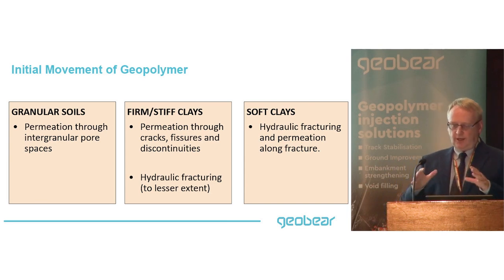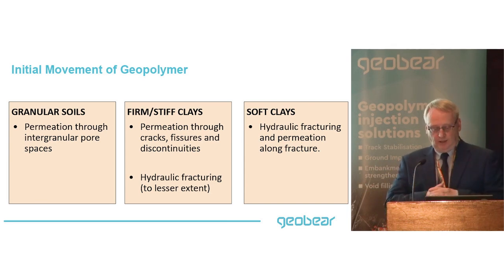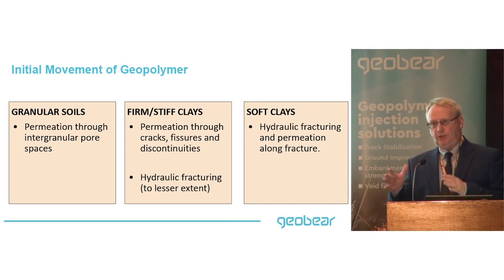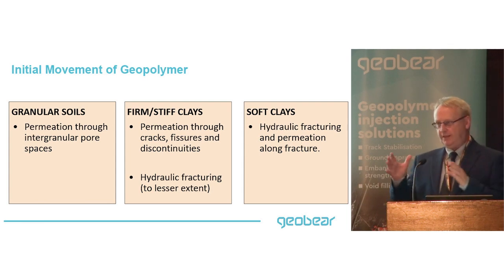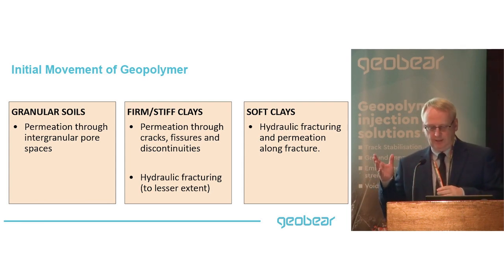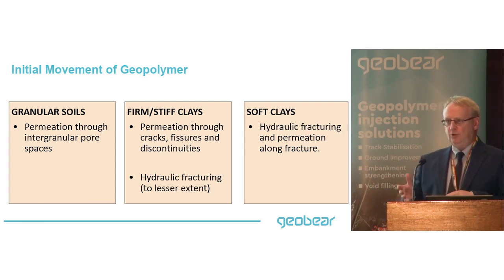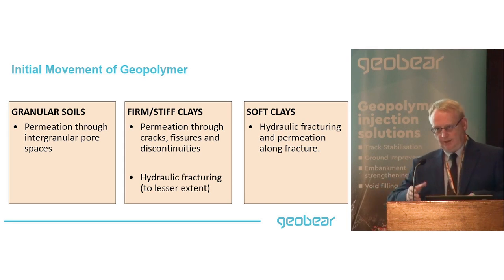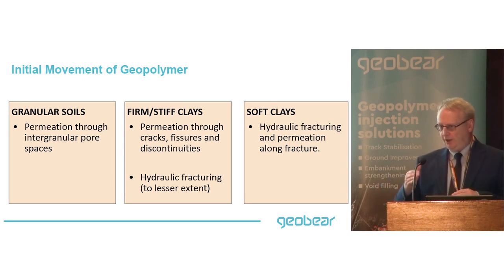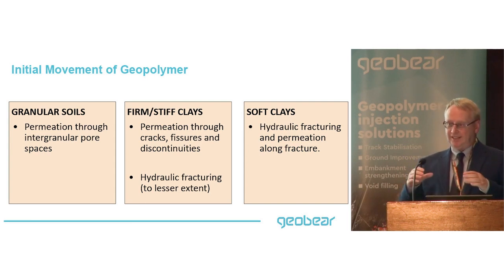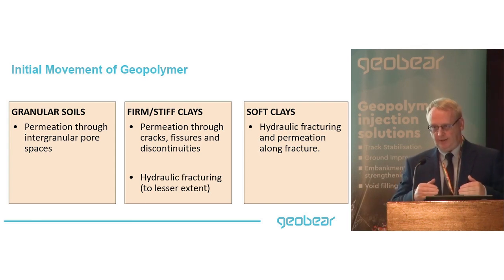When you're dealing with a firm or stiff clay, typically in clay shrinkage solutions where we have a desiccated fissured clay, the polymer will migrate along the fissures and voids, not through the clay itself. That means there's less of what I call hydraulic fracturing.